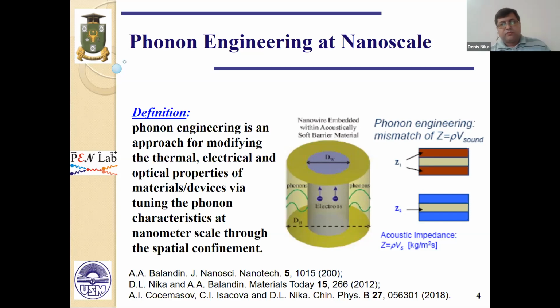Why are the phonon properties so important for us? The answer is quite simple, because they determine the thermal conductivity, and also scattering of electrons on phonons limits electrical conductivity at moderate and high temperatures in semiconductors. And thermal conductivity itself is an important characteristic of material, because for efficient thermoelectric conversion, we need materials with low thermal conductivity and high enough electrical conductivity.